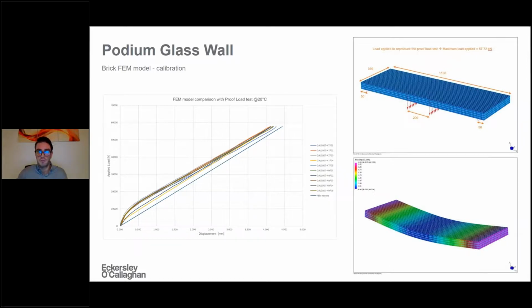So because we had to do this 4-point bending test, and because we were asked by the approval authority also to provide some brick models of the flat and curved panels to justify the analysis, we took the occasion of using the 4-point bending test also as a way to calibrate our brick models and show to the authorities that the accuracy of the modeling was quite good. And as you can see here, this model basically tried to reproduce exactly the 4-point bending test glass setup.